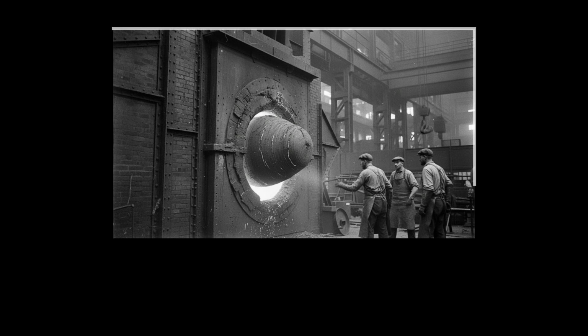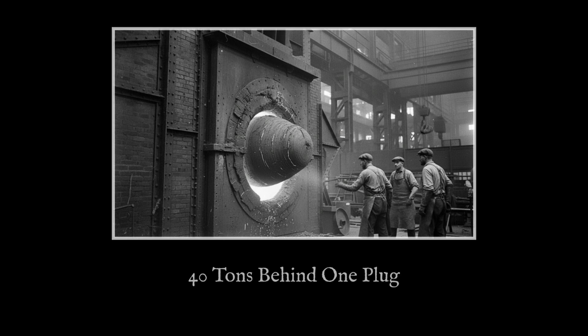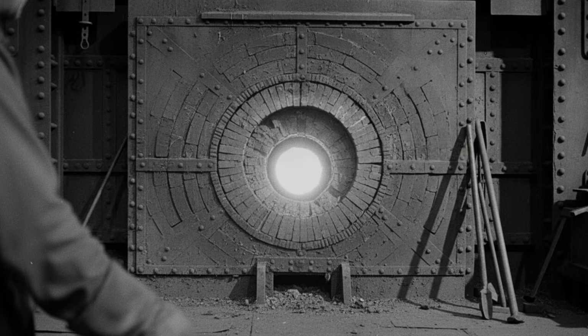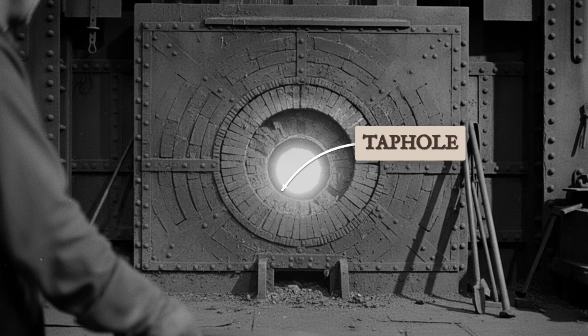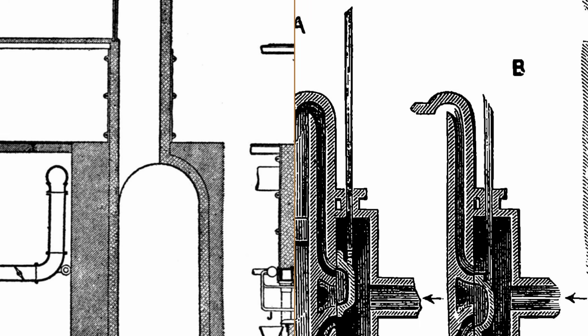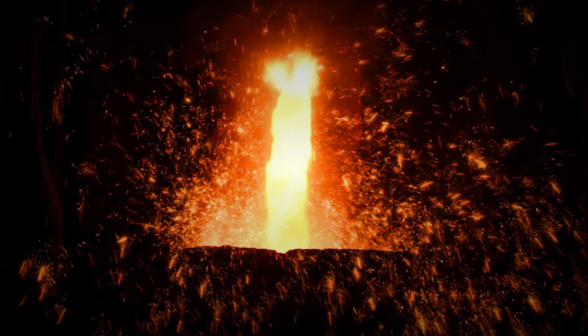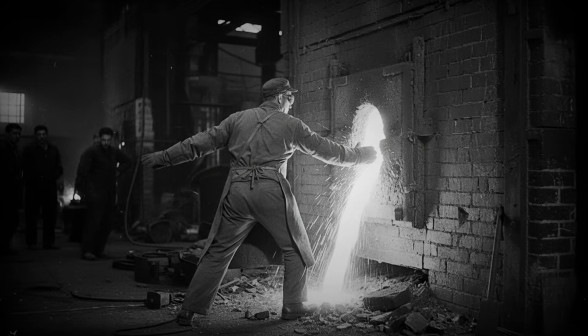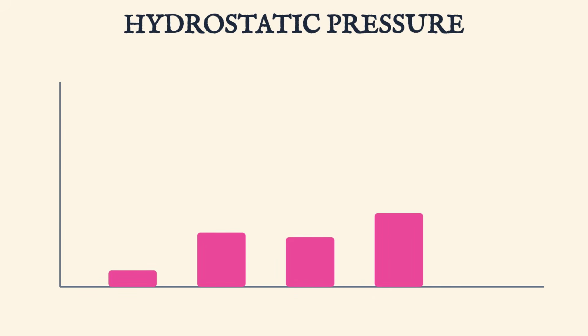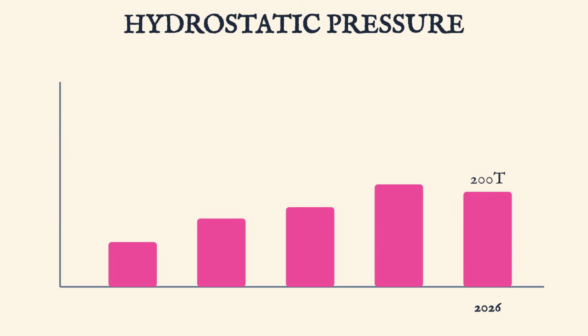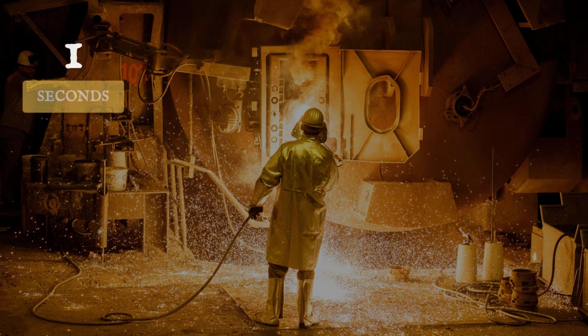What that description underplays is the physics of what was happening behind the plug. The tap hole was in the back wall of the furnace, at a low point in the hearth where the liquid steel collected by gravity. Behind it was the full weight of the heat pressing forward, not just its own mass, but the hydrostatic pressure of 200 tons of liquid metal at 2,900 degrees Fahrenheit, finding the lowest available point.